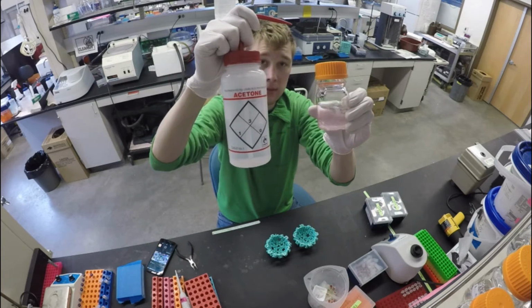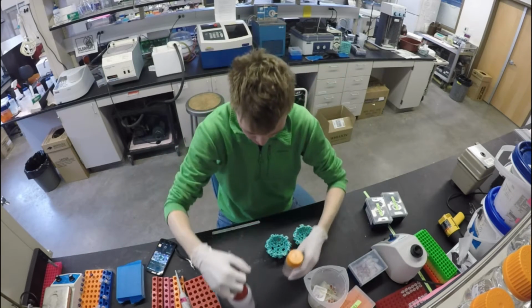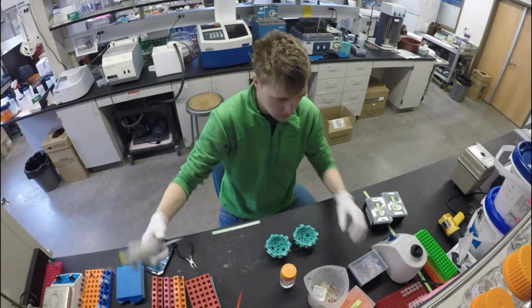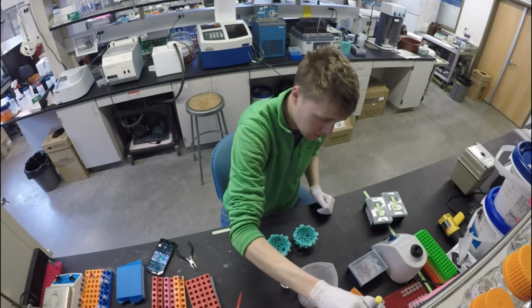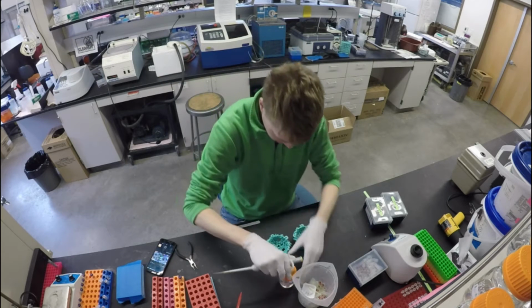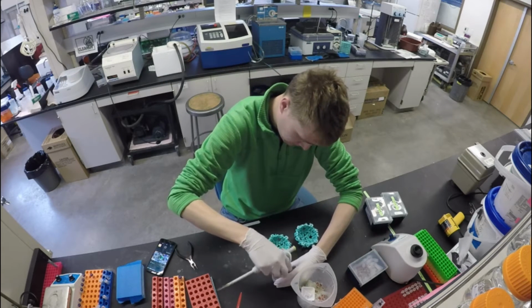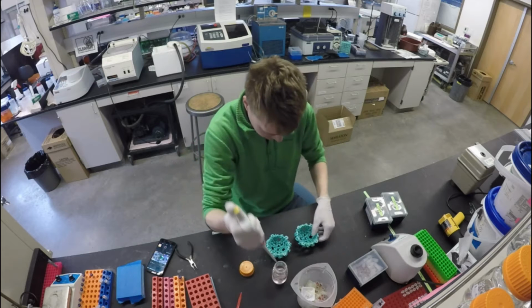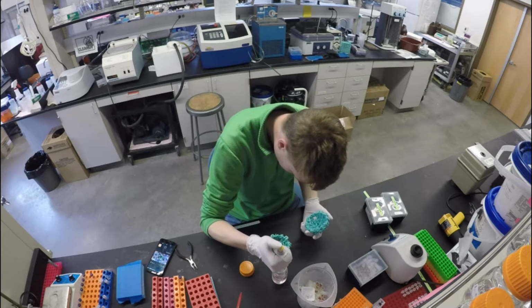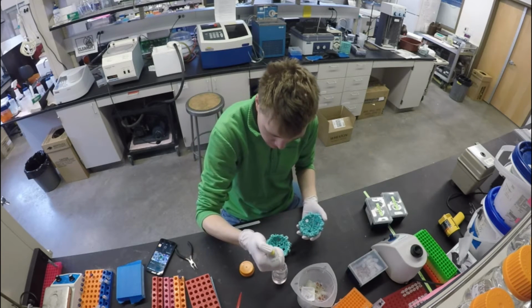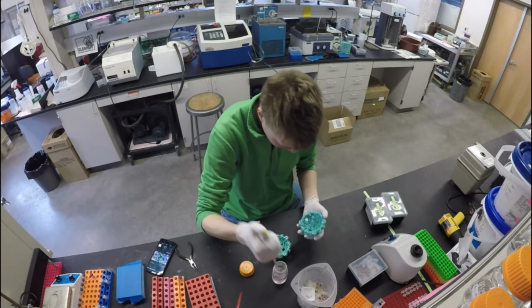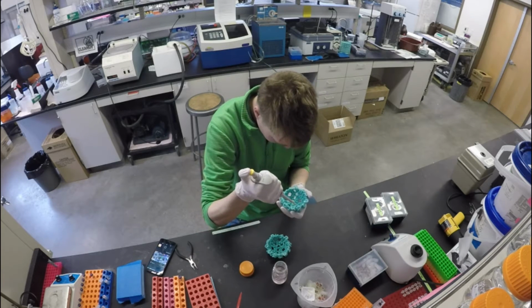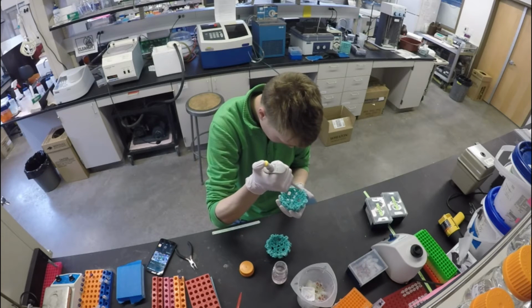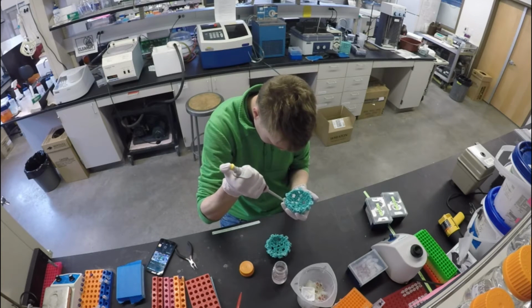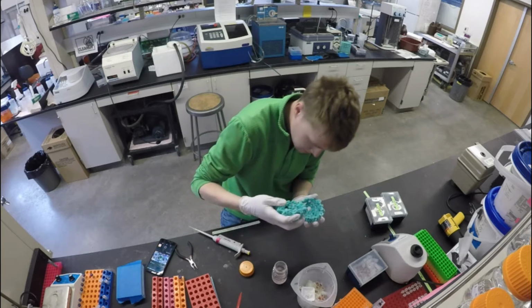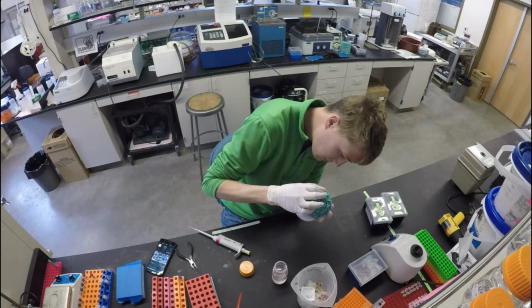I'm going to take some acetone, that's why I print in ABS. I can then just apply a little bit of acetone to these parts and it will partially melt the plastic, and we'll be able to glue them together. Makes it nice and easy. Just apply a little bit here on all of the little pieces. Okay. Then what I'm going to do is line up those dots with each other, and I'll